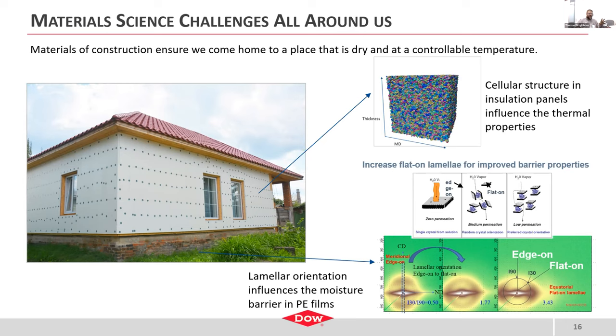A third way that heat propagates from one side of a material to the other is the radiative heat transfer. So if you think about heat as an infrared wave, you want it, as it propagates from one side of a material to the other, to interact with and scatter from as many points as possible between the start and end point. The way to do that is to decrease the cell size of the resulting foam. Understanding the cell size and the formulation variables that have an effect on cell size is a major research thrust in the thermal insulation market.